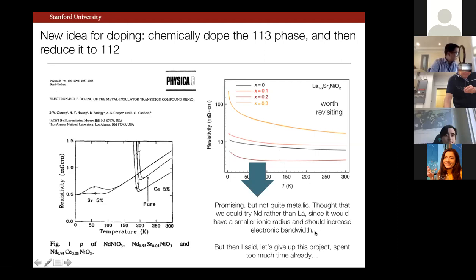And I like to quote a mentor at that time when I was at Bell Labs, Hidenori Takagi, who was a visiting scientist at the time. He told me that for layered oxides, when you get to the scale of about a milliohm centimeter, this starts to be right at the threshold where you can induce coherent states, and interesting things happen: superconductivity, charge density wave phenomena, and so forth. So the idea was simply to say, okay, lanthanum looks close. Why don't we go to a smaller ionic radius in neodymium, and perhaps that should increase the electronic bandwidth in the system.